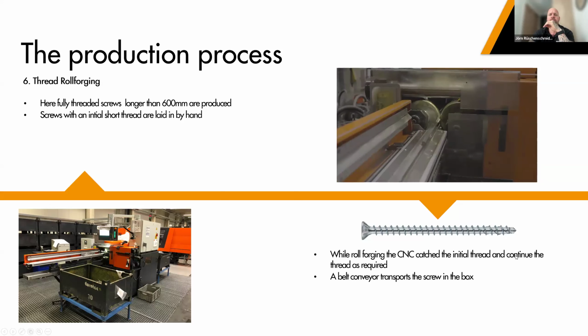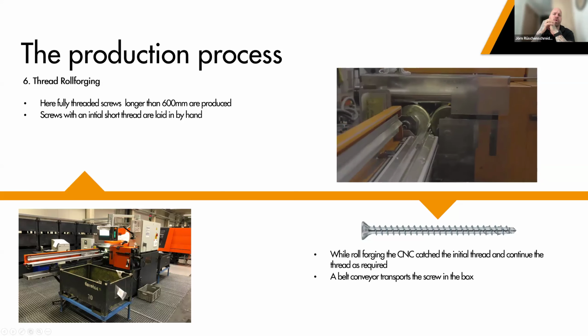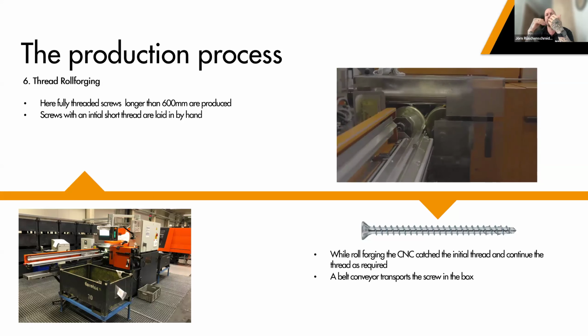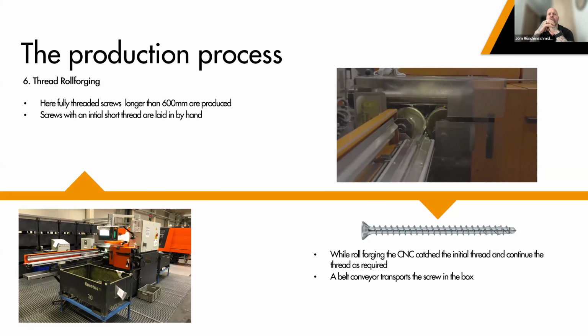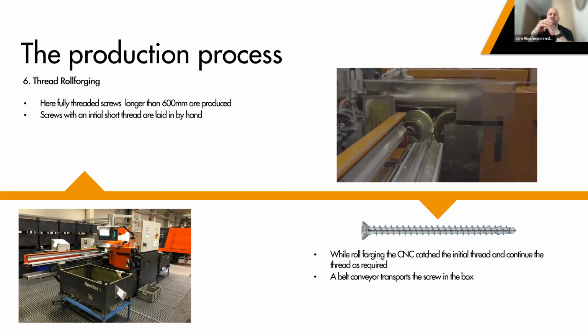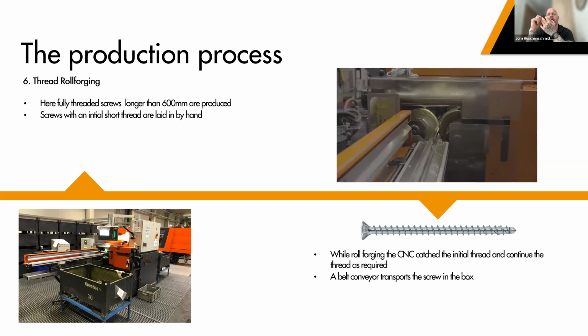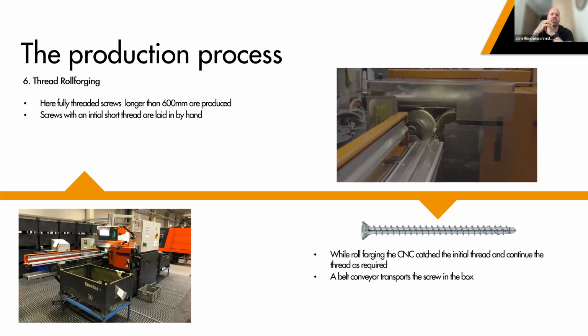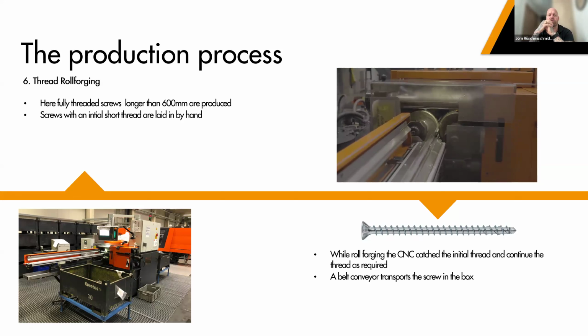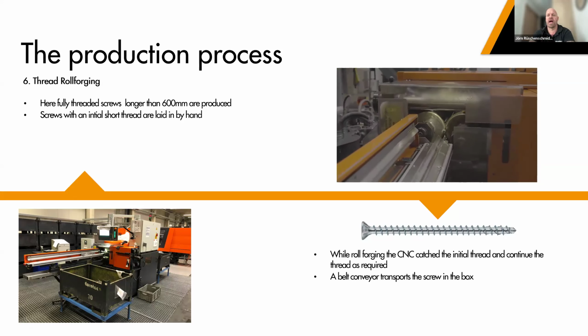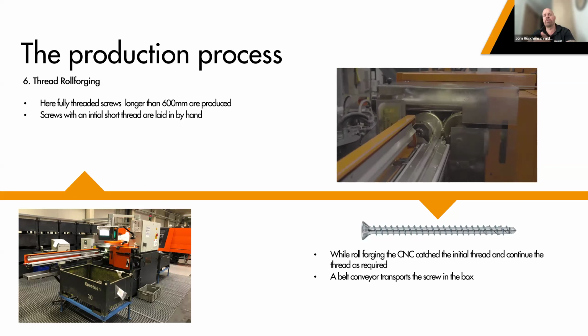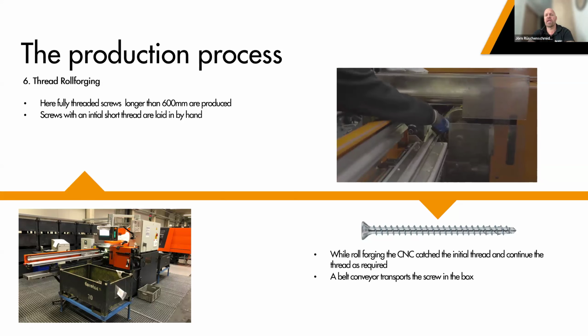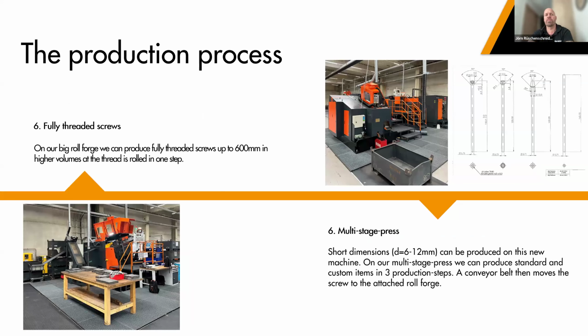Yeah, it's a bit stuttery, but now the screw gets moved in between those two rolls and becomes a fully threaded screw. This is how we do big diameters, so 10 or bigger, so 10, 11.3, and 13 in our case, of 600 or even up to 1.4 meter, which is the longest screw we produce in the facilities in Hagen. If we have a screw up to 600, we either can produce them like that, which wouldn't be efficient by numbers. We mostly do this on a big roll forge you see on the bottom left.